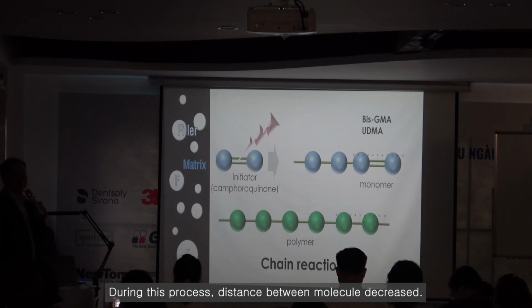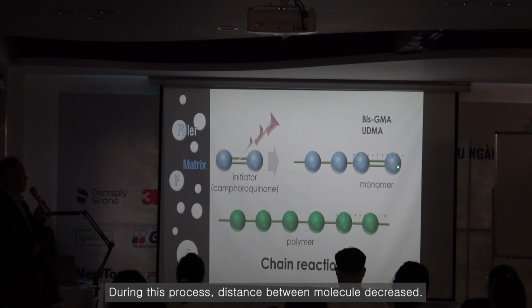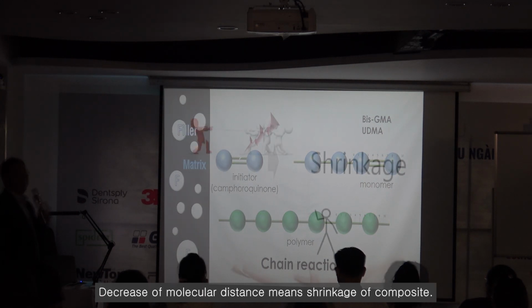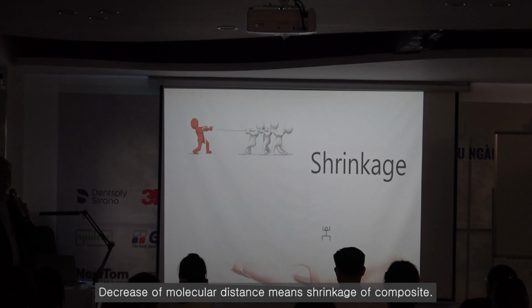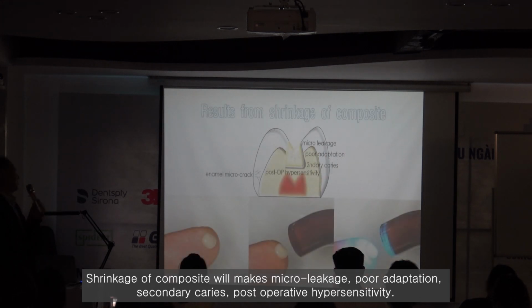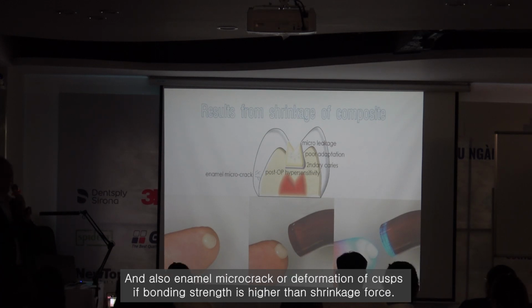During this process, the distance between molecules is decreased. So the decrease of molecular distance causes shrinkage of the composite. The result of composite shrinkage is microleakage, poor adaptation, secondary caries, and also post-operative hypersensitivity. Sometimes an enamel microcrack or cuspal deflection occurs when the bond strength is higher than the shrinkage